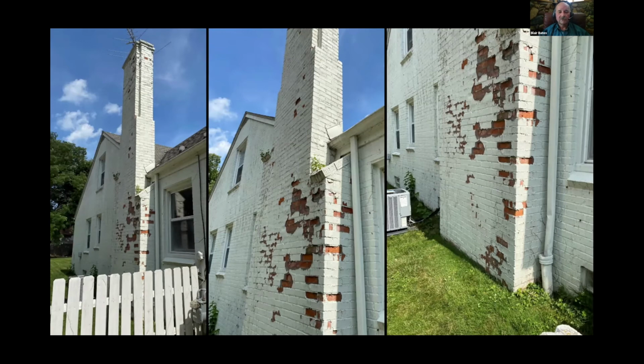Yeah, for the age of this, I'd use what's called a type K mortar, which is 3 parts lime, 1 part Portland cement, and 12 parts of mason sand. And then patch them back and tool it so it looks like your brick house again. And then when it cures, 1 year later for lime, if it's an inch thick, so maybe 6 months later, you don't need to prime it. And you'd use a masonry paint, something that's alkali resistant.